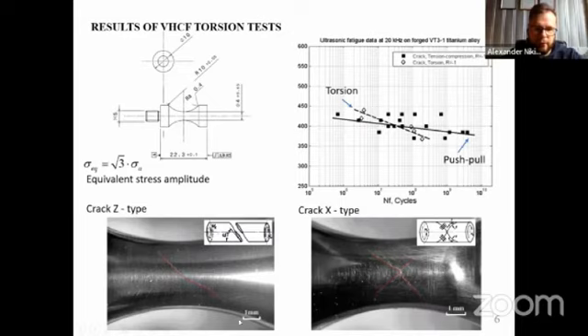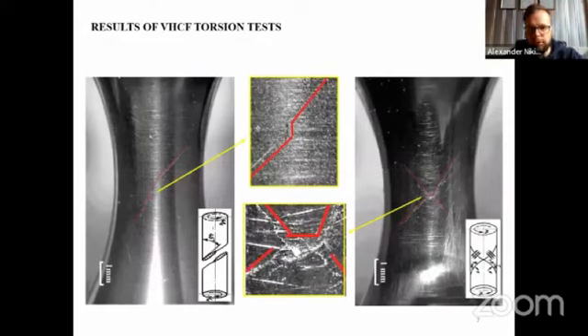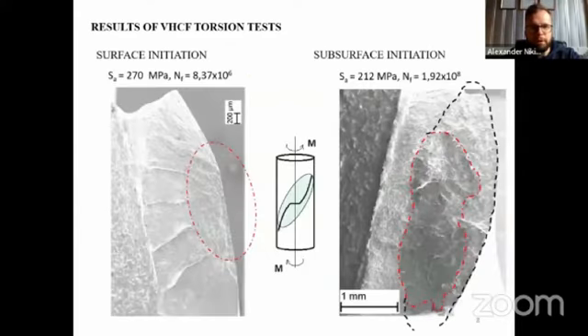If we look at the lateral surface of the specimen, we normally have two types of crack. Sometimes we observe just a single main crack lying in a plane at 45 degrees. Sometimes we have a double crack, similar to an X shape. We were trying to investigate what the difference in the spatial shape of the crack is, depending on the mechanism of crack initiation. Here you have a little more detail of the crack growth, and we have to pay attention that during the initial stage, we have a small part where the crack is growing in the plane of maximum shear stress. It means that at the initial stage, we have pure shear as the driving mechanism for crack opening.